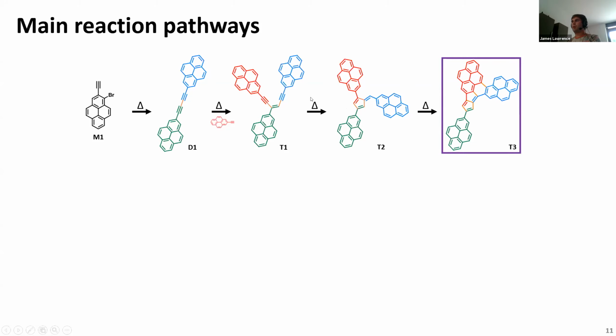So while the Glaser coupled dimer, this open trimer, and this fused trimer are quite common, we only see a few of these, which may indicate that when it's formed from this, it very quickly reacts and forms this. Now, I very deliberately haven't shown a reaction mechanism here because there's probably several going on at once. For example, some of these species may have radicals which immediately react and form the next species and so forth. But we do see all of these intermediates in what appear to be a hydrogen passivated form as well.